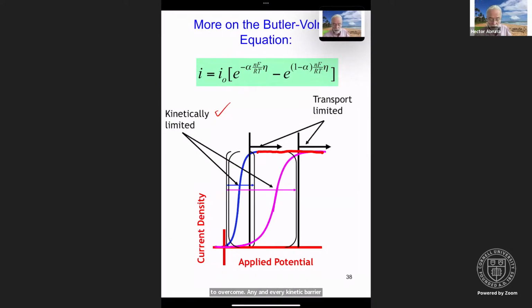If you have another process that is more sluggish, then in order to achieve the same current density, you have to apply a much higher overpotential. And so again, this tells you that K for the blue is bigger than for the magenta line here. The point here is that you have a regime where you're kinetically controlled, followed by a regime where you're mass transport controlled.